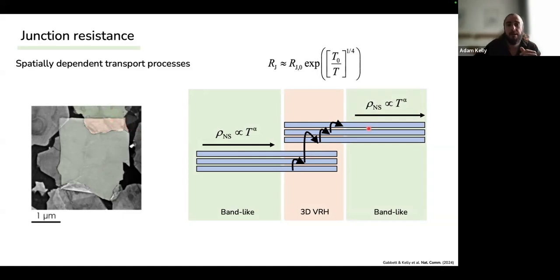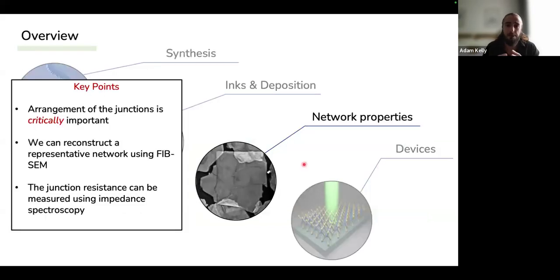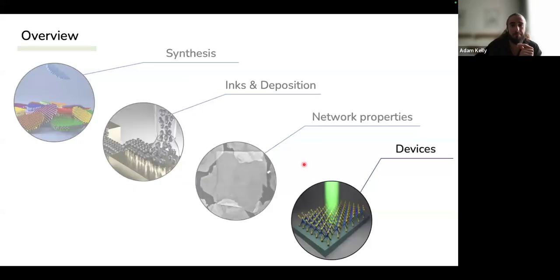So this means if we have a network limited by the junctions, to improve the network properties like conductivity or mobility and bring it up to a band-like process, we need to focus on the junctions to reduce this junction resistance as much as possible. So the key point when it comes to network properties is that the arrangement of the junctions is critically important if you want to have good properties in a network. We can also do reconstructions using FIB-SEM so we can visualize how much porosity is in there. And we can actually measure this junction resistance using impedance spectroscopy.